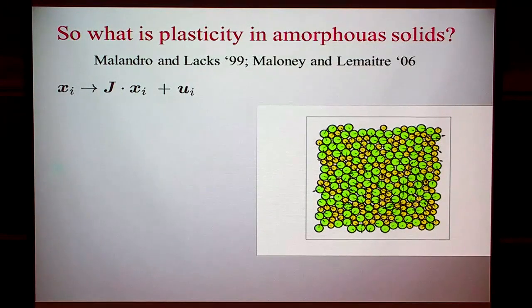And now you look at the forces between the particles. The forces were zero before the application of the external strain, and now the forces are complex, random, and pointing in all directions. The system is not in mechanical equilibrium, and if you want to bring it back to mechanical equilibrium, there is a second, non-affine step that needs to be done. This is the thing. So I'll show it once more.